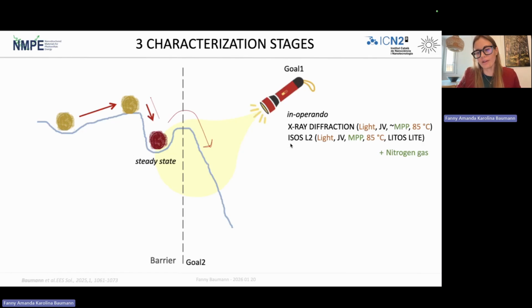So one is an operational stability test using ISOS-L2 conditions with white LED illumination, 85 degrees, and under maximum power point tracking in LITOS LITE. And the second experiment is going to be with in-operando X-ray diffraction using light and 85 degrees, again in very similar conditions, but holding the cell at an approximate MPP point after taking several JVs during the experiments.